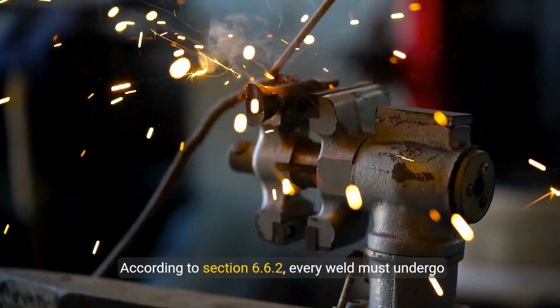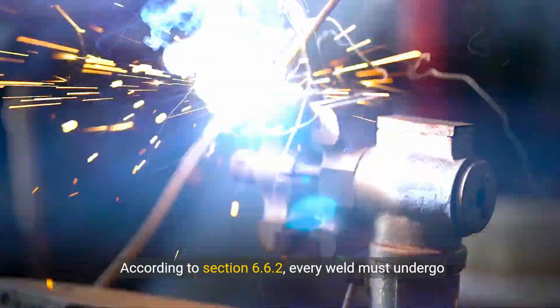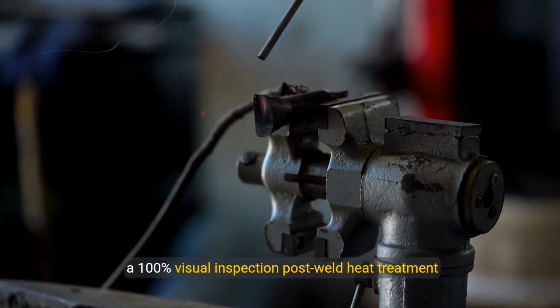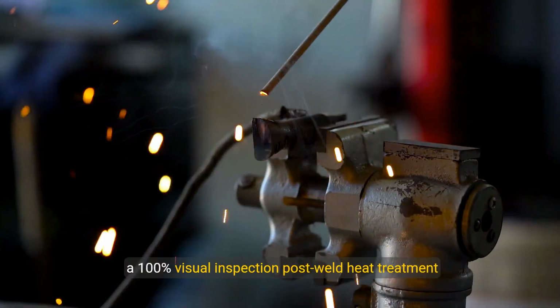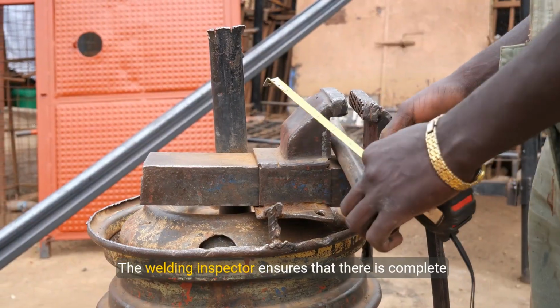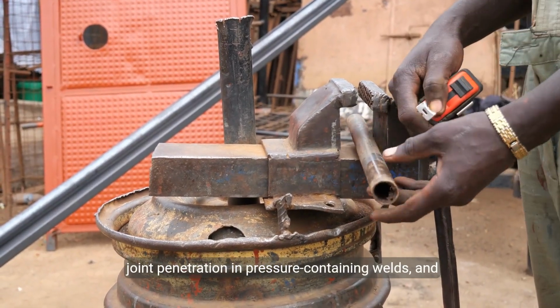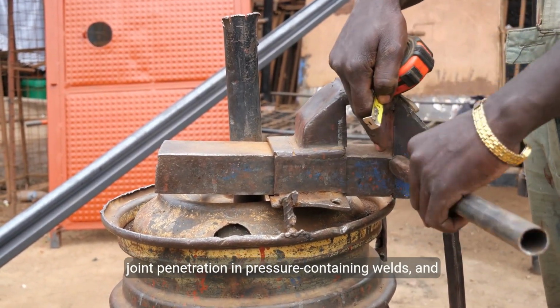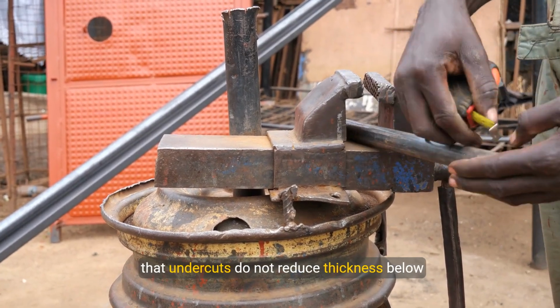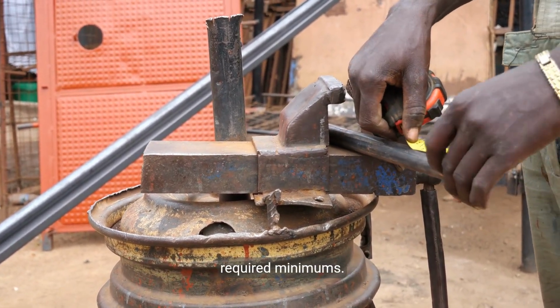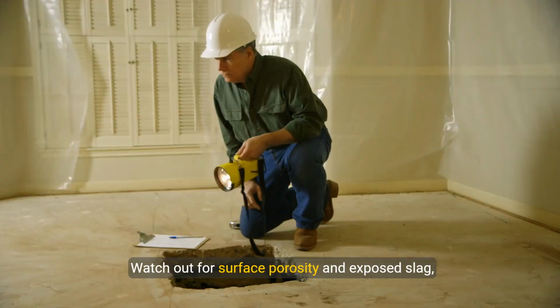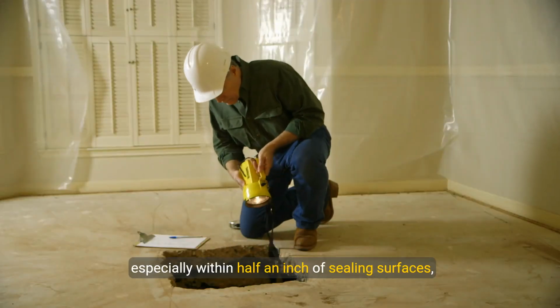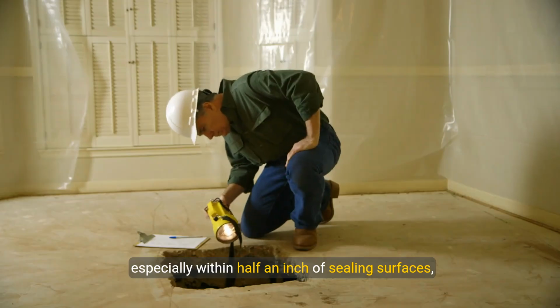According to Section 6.6.2, every weld must undergo a 100% visual inspection, post-weld heat treatment, and machining. The welding inspector ensures that there is complete joint penetration in pressure-containing welds, and that undercuts do not reduce thickness below required minimums. Watch out for surface porosity and exposed slag, especially within half an inch of sealing surfaces, as